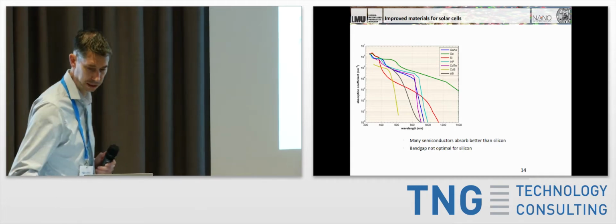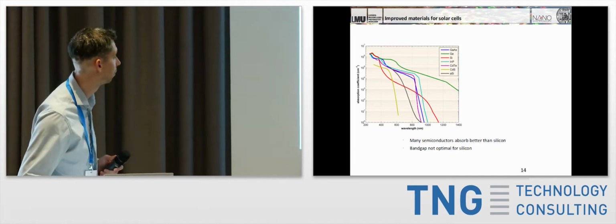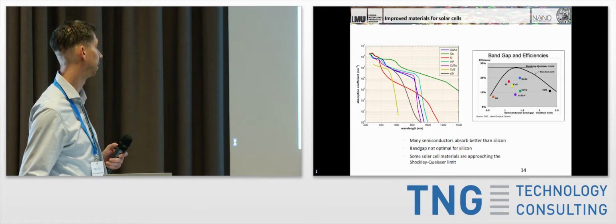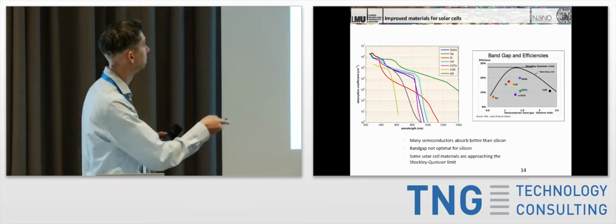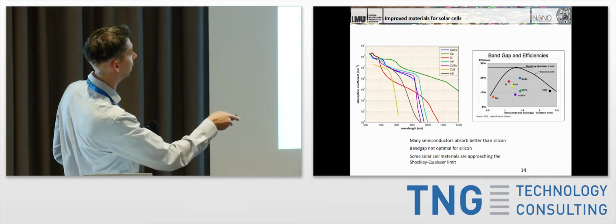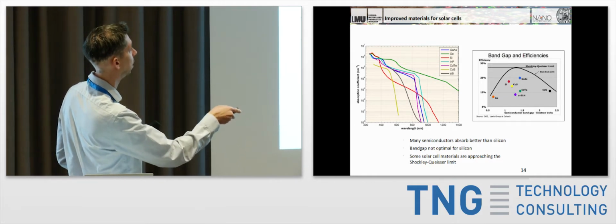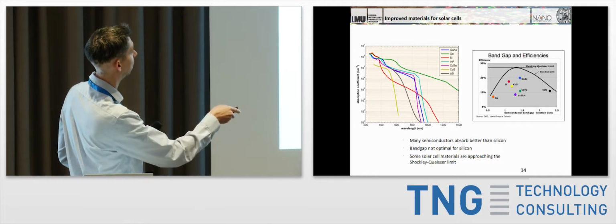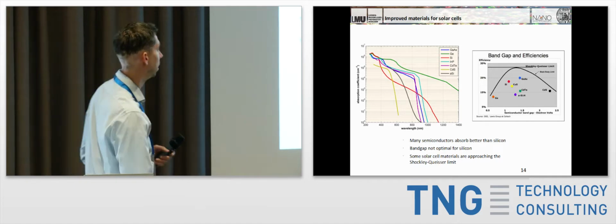Also, another problem with silicon is that the band gap's not optimal. I said 1.3 is actually optimal for that. Silicon is slightly off that. And so you can see this is where silicon sits. So this is that top curve from the black curve that I showed you before, essentially limiting it. And you can see silicon's not exactly at that optimum point, but close to it.